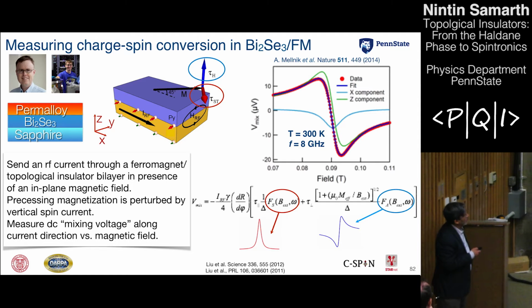So you basically apply a magnetic field at some angle. You set the magnetization of the ferromagnet into precession. And you monitor the precession by using a DC voltage technique. So it's a very simple idea, which is complex in its details, but the measurement itself is basically measuring a DC mixing voltage in this direction as you sweep a magnetic field. And as you sweep your magnetic field, you take this precessing ferromagnet into resonance, right? It has a certain precession frequency, which is determined by the magnetic field. And when that precession frequency matches the frequency of the RF current that you're driving through, you get some resonance effect.